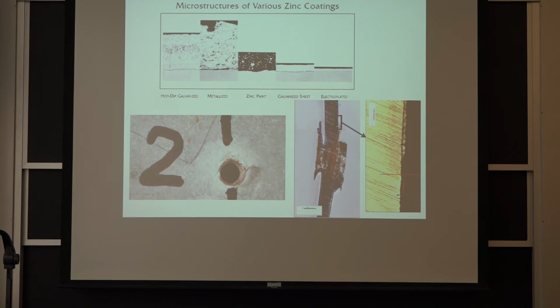The chain that I circulated, one big problem with that one was you lose the coating. So it's going to rust there. Now, if it's an application in water, you can use cathodic protection. It's a perfect case to protect the areas that get scratched. A lot of times when you have cathodic protection, by the way, we put that on all the big transmission pipelines. They're coated, and then they have cathodic protection for where the coating breaks. If you didn't put a good coating, you'll use too much current. It will really not be efficient to try to protect bare steel underground. But the idea is during installation, there's going to be some damage, and your coating is not going to be perfect. That's why you use a combination of the coating plus cathodic protection. And that was the case for the storage tanks that we talked about last time as well. It was coated plus cathodic protection.